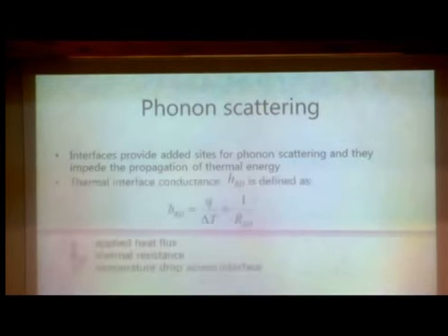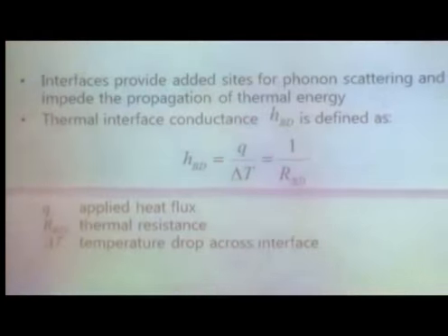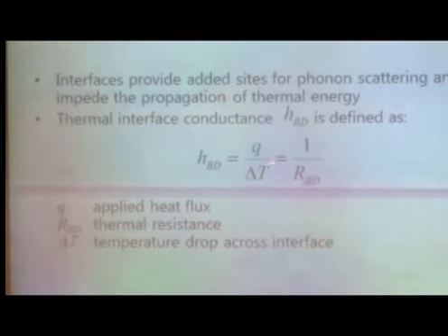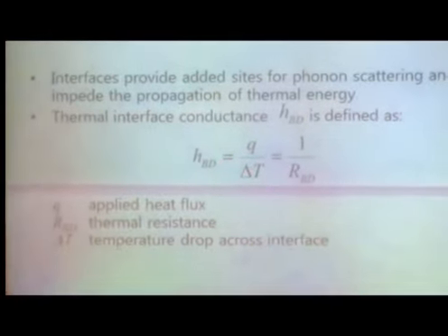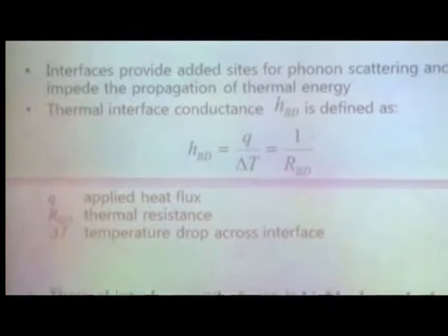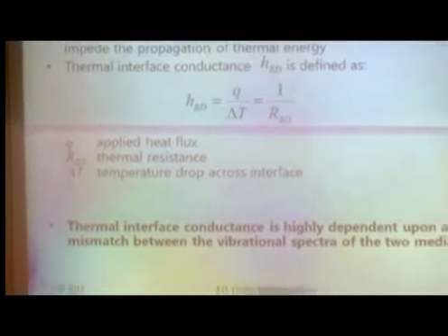So, in order to know a bit more about this, we need to look a little bit at phonon scattering. We know that interfaces provide added sites for phonon scattering. And we can define a thermal interface conductance as the applied heat flux divided by a temperature drop across the interface. And this is very important, that's why it's bold, of course.